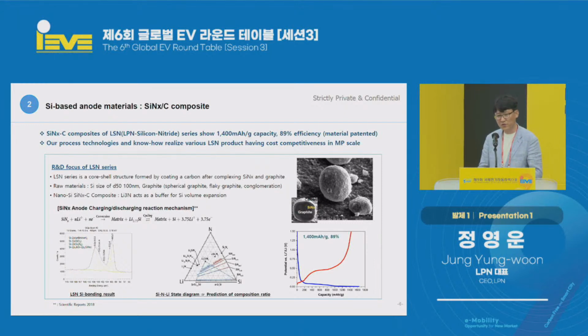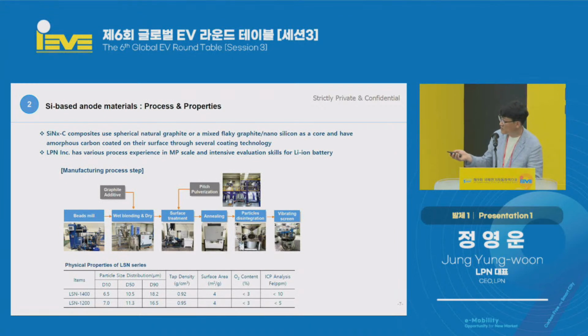When you look at the structure, nanosilicon is pulverized into 100 nano, so it's very tricky to handle. So we are using massive core, and on top of that, we are coating the silicon. And we finish that off by isolating with carbon. And with that technology, we can achieve very high performance, but it's very difficult to create nanoparticles, and that requires a lot of capital expenditures.